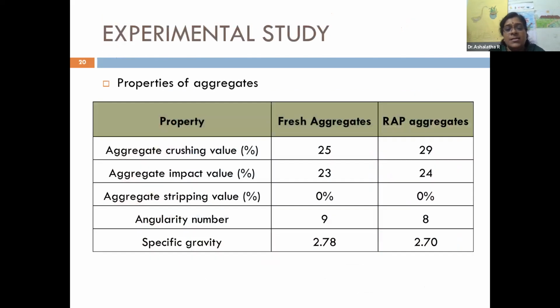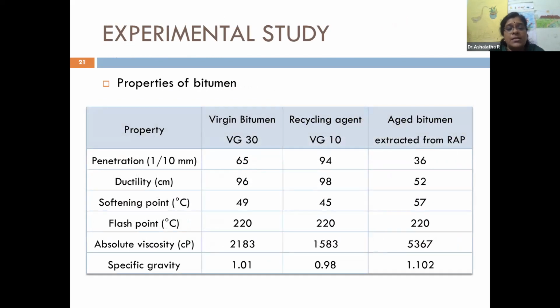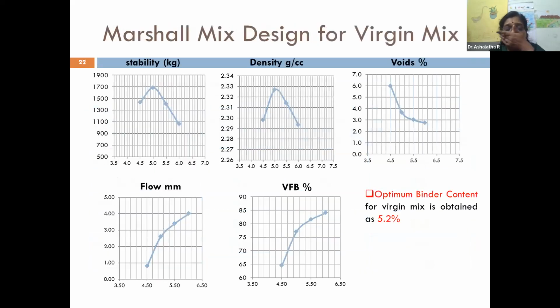Then we tested the properties of the fresh aggregate and the RAP aggregates, and also the properties of the virgin bitumen, that is VG30, which we used, VG10, which was used as a recycling agent, and the aged bitumen extracted from the RAP. All the various properties of bitumen were tested, and that is shown here. We also conducted the Marshall mix design for the virgin mix, and the optimum bitumen content for the virgin mix was obtained at 5.2%.